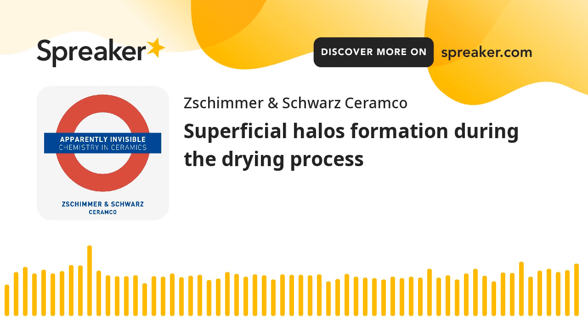It is also important to pay attention to the chemical composition of processed waters. Why? After a careful study of their features, it's important to check the presence of those anions and cations that can be responsible for the halos that, as we said, can be visible even after the firing process. What does that mean? It means that it would be great to limit the presence of anions and cations of inorganic origin that tend to create soluble salts within the processed water.